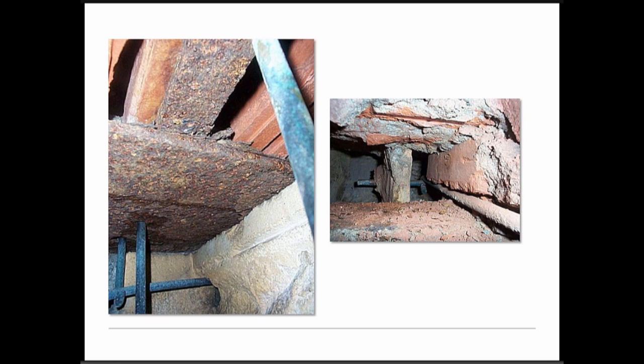Sometimes non-corroding materials such as copper alloy anchors, hooks, and dowels are used to support units. However, they all ultimately connect back to ferrous metal beams, angles, or structural support elements, which remain prone to corrosion and can cause distress in the units.